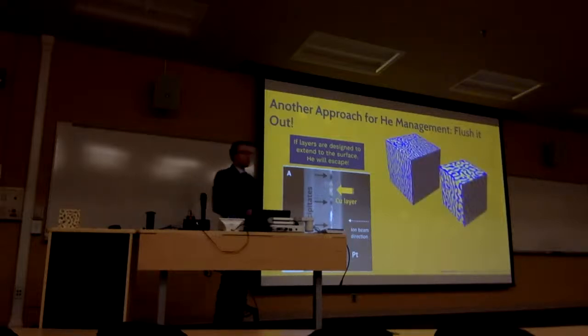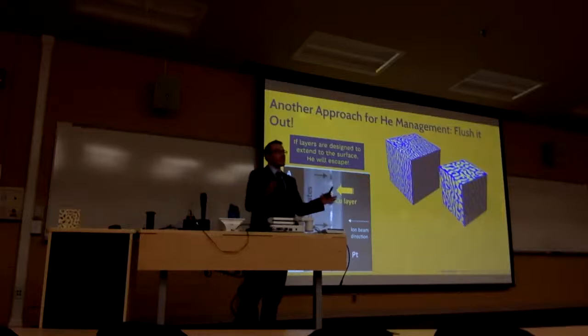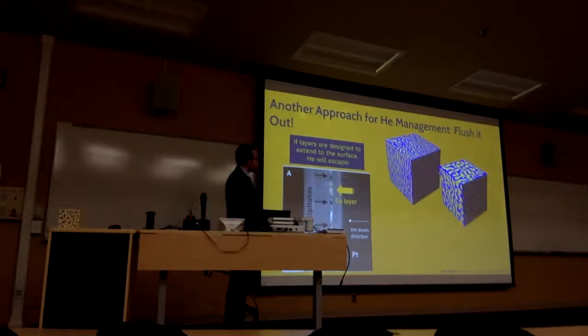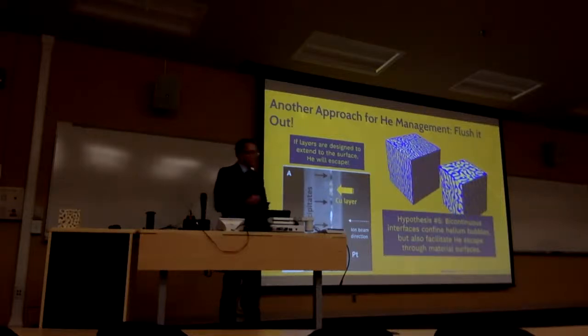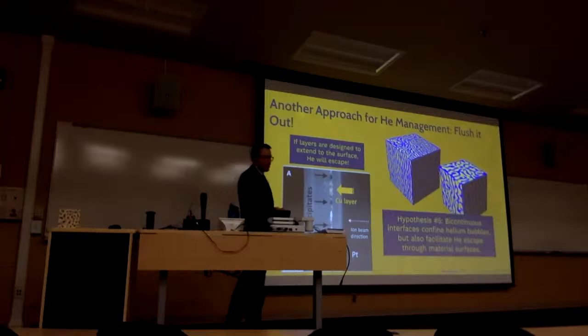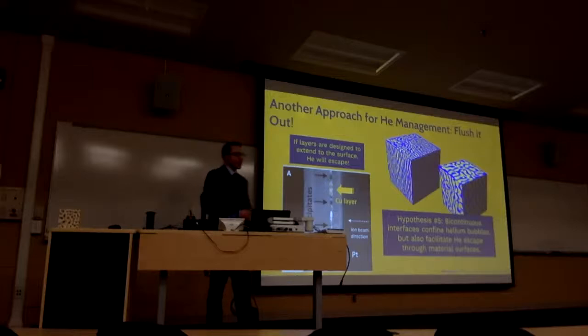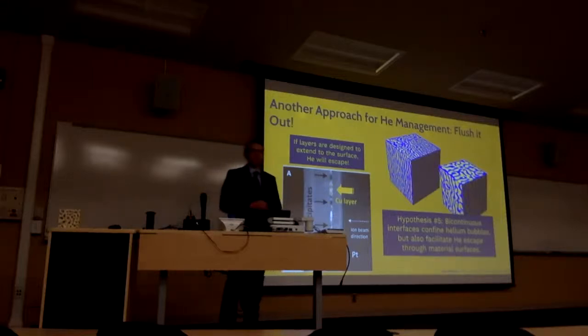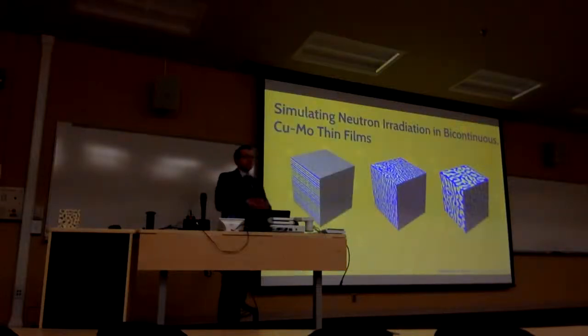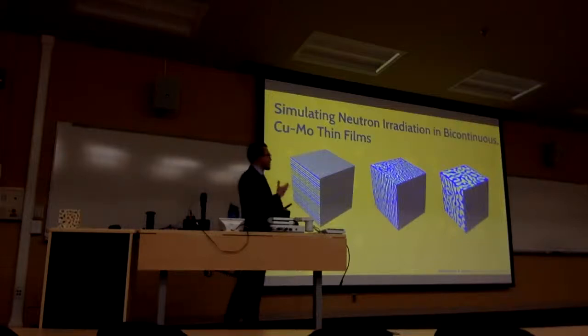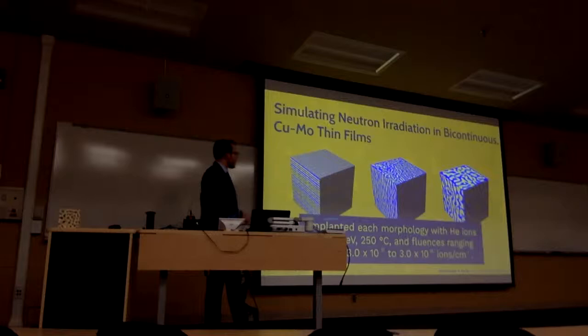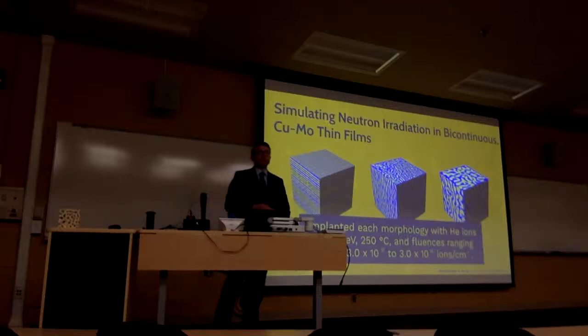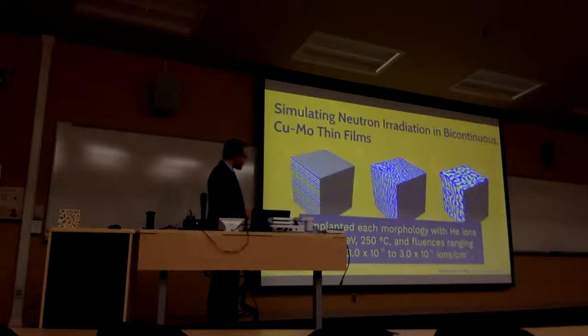Well, we have very interesting structures that do have interfaces that extend in 3 dimensions to the surface. And so we asked the question, what if we were able to implant these samples with helium and see if there was a development of nanochannels to allow for the escape of helium in a nuclear environment? Our hypothesis is that these bicontinuous interfaces that extend to the surface can facilitate helium escape through the surface. We simulated a neutron irradiation environment by implanting helium into these 3 different structures at a certain energy and temperature and a range of fluences of helium ions. And I want to describe to you one of the results in the structure.